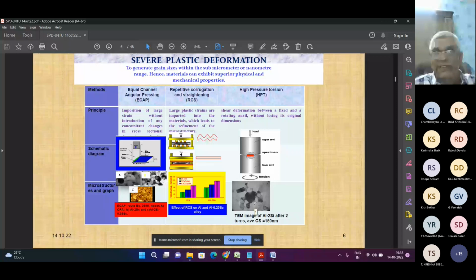In this process, you can see in the middle diagram, the sample is kept between the anvil, which has a curved type. When large plastic strains are imparted into the material, it leads to refinement of the microstructure. Initially the sample becomes corrugated in nature. Then you take two flat dies and press it, and it becomes the flat original sample again. Again you do the process in one direction, and you can go on changing the direction, and you can get very good grain refinement here. We have shown how the mechanical properties are changed in this process, and I will come into the details later.